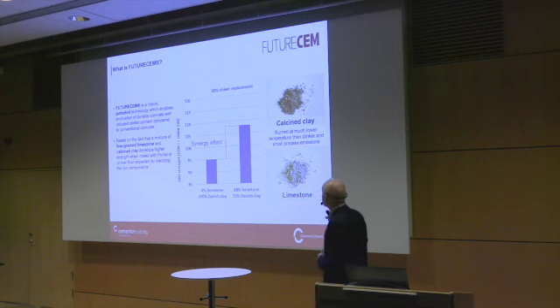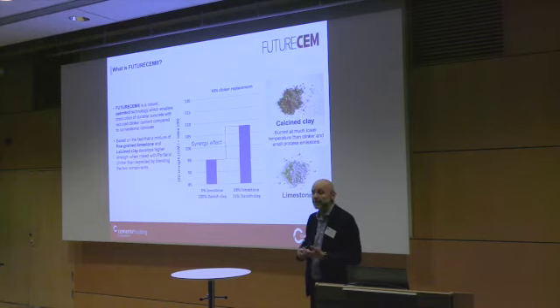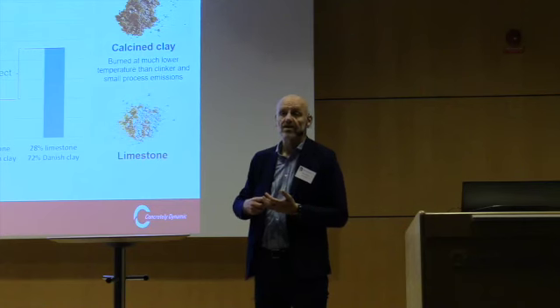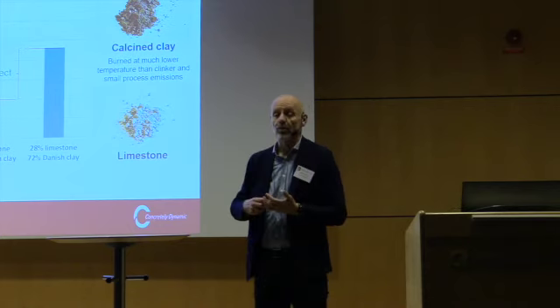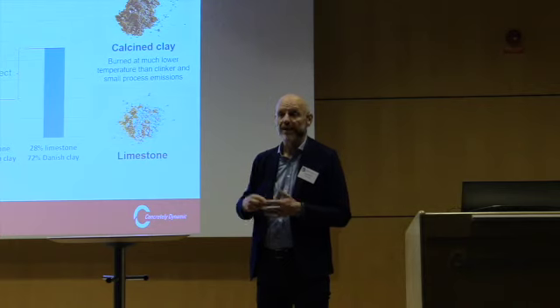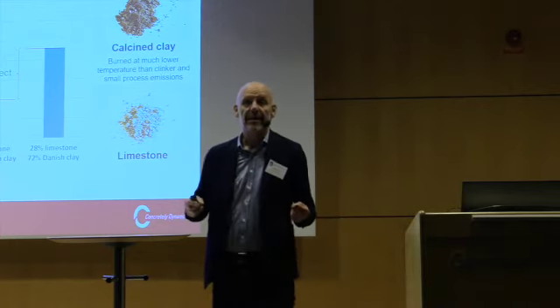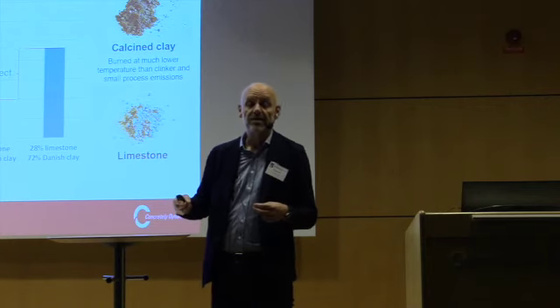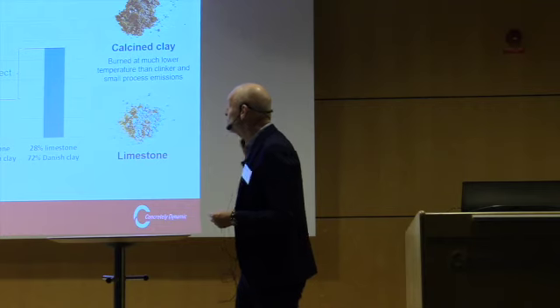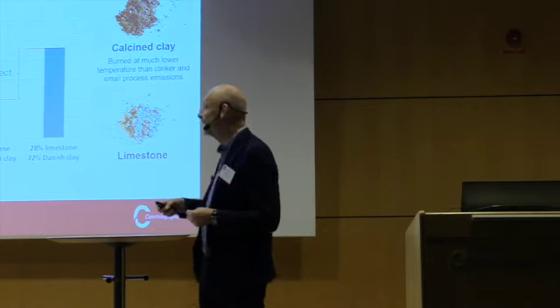And what I show here is in fact one of the first tests we did. We replaced 30% of the clinker by this calcined clay, and you can see a picture here of the type we used. Then we added some limestone, and there was a clear synergy effect. We get these carboaluminates which react together, so there is an increased strength compared to what it would have been otherwise. This is really the basis of the technology that enables us to reduce the clinker content more than we would have been able to do if we'd used just the pure calcined clay.